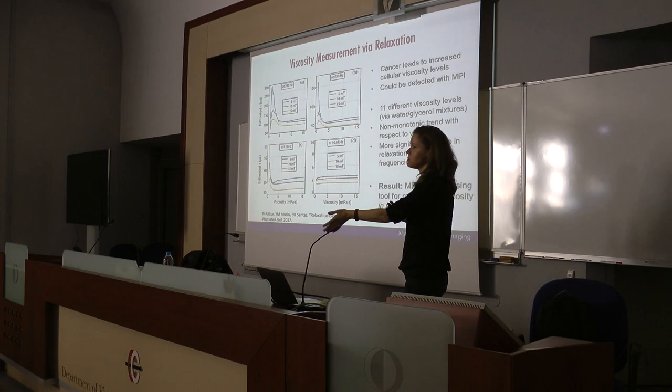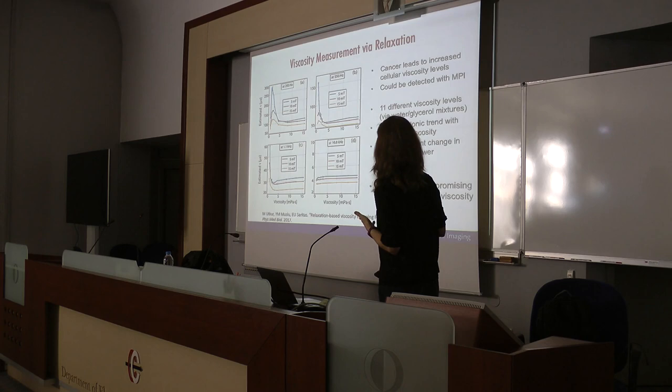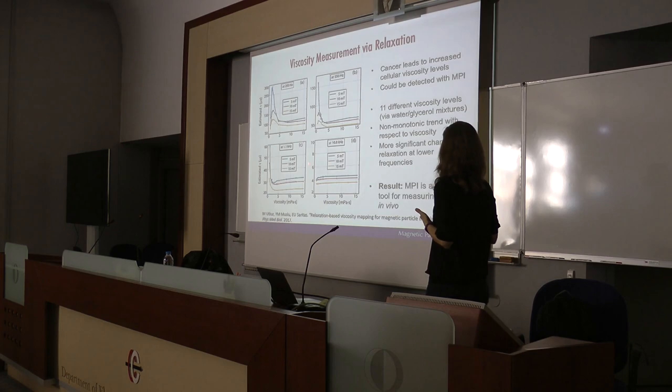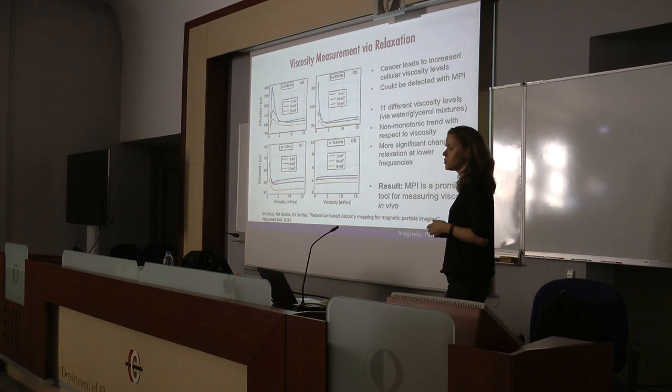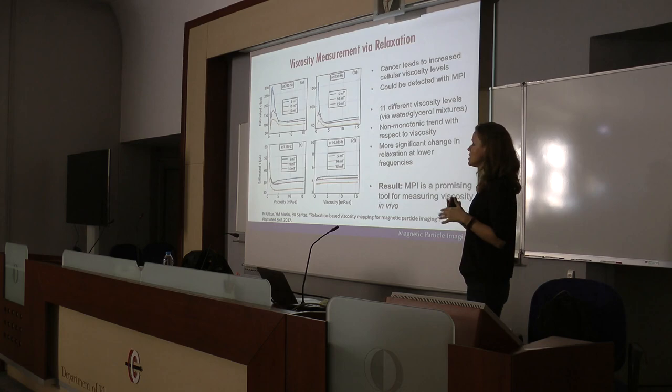We performed experiments on our NPS setup to show that with this time constant estimation technique, we could distinguish the viscosity of the environment the nanoparticles were placed in. The x-axis is the viscosity of the environment and the y-axis is the estimated time constant. We performed experiments at different frequencies and AC field amplitudes to find which frequency is most suitable for viscosity mapping in MPI. We found the best one-to-one mapping between viscosity and estimated time constant is achieved at around 1.1 kHz — notably far from the 20–25 kHz typical for current MPI systems, suggesting that moving to lower frequencies provides additional information from the nanoparticles.